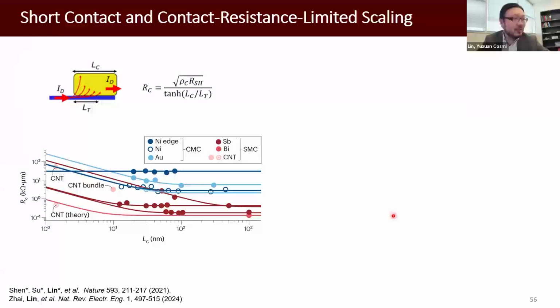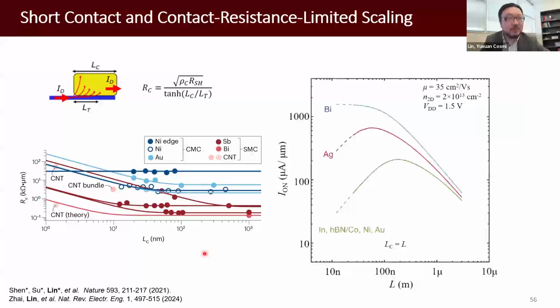We also have some systematic comparison in the literature about the contact length. The length of the metal contact also needs to be greatly reduced. Here is some summary. All the reddish ones are the semi-metal contacts, so they can also give you good scaling capabilities. Based on that, we can anticipate the on current versus different channel length, but the contact length should be scaled simultaneously. For bismuth, we still see this plateau that's saturation velocity limited. For all other metals, they are contact length limited.